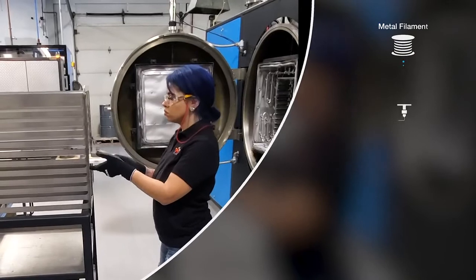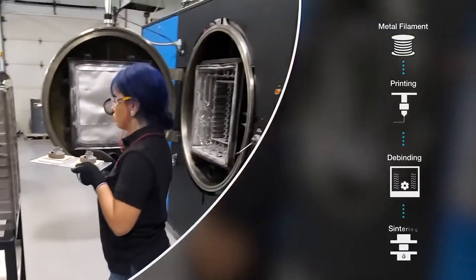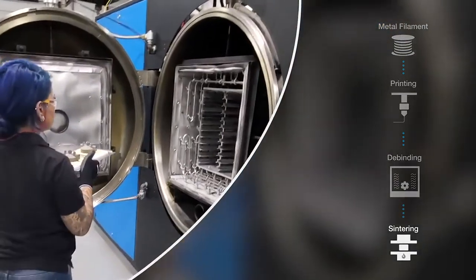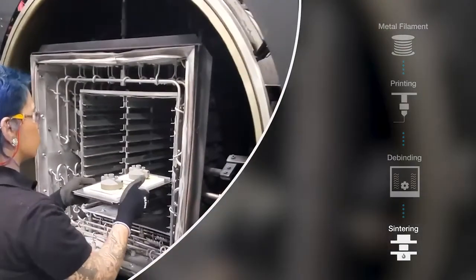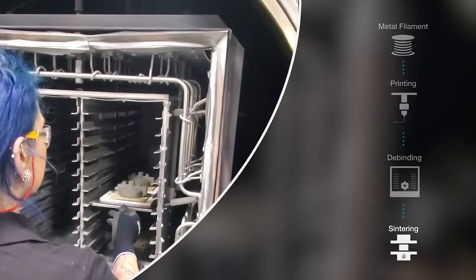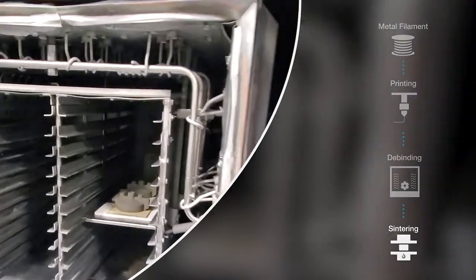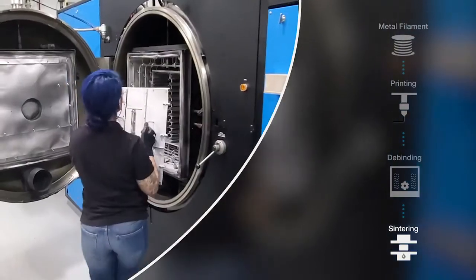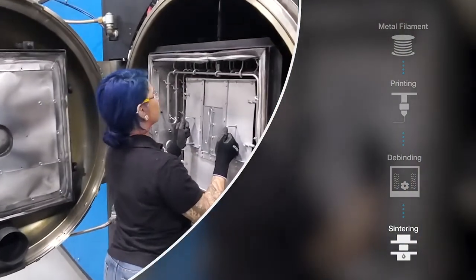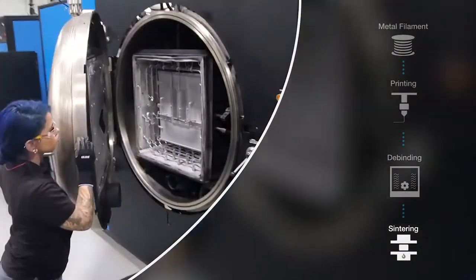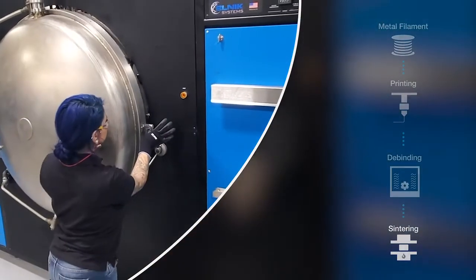Now your part's been debound, it's now what's called a brown part, and it's ready for sintering. Put simply, sintering is just combining the metal particles into a solid part using temperatures and pressures. In this case, it's around 1400 Celsius for 316L. Now, this is also where you're going to see that shrinkage, where you're seeing 20% in Z and 16% in X and Y. That is oriented with the print method. So the Z level, with the layers, that's the direction that's going to shrink the most. So it's important to understand which way the part is going to be set up and how to properly scale it.